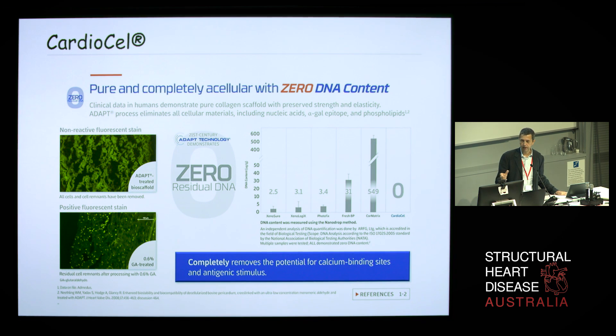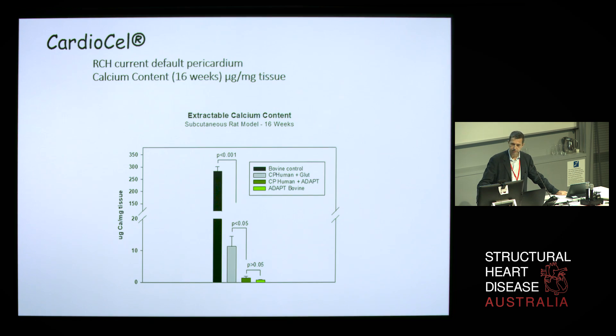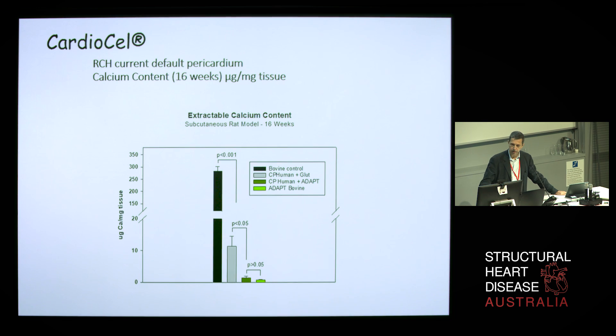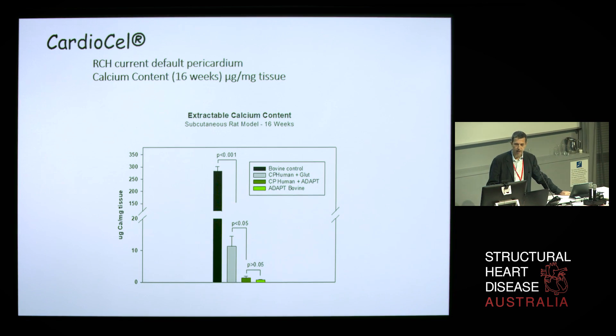Another characteristic is that the tissue is totally decellularized and there are no DNA remnants, which has a very strong implication in calcification. In these four groups, you can see that the light green — the ADAPT or CardioCel treatment — has virtually no calcification in the subcutaneous implantation in the neonatal rat, which is extremely discriminant and very powerful.